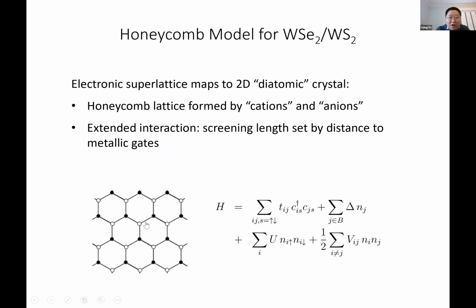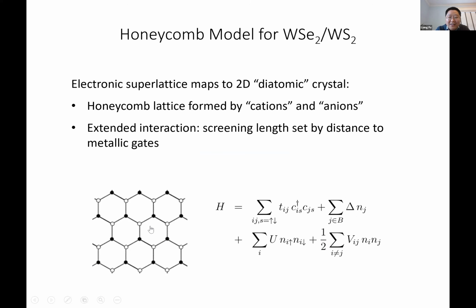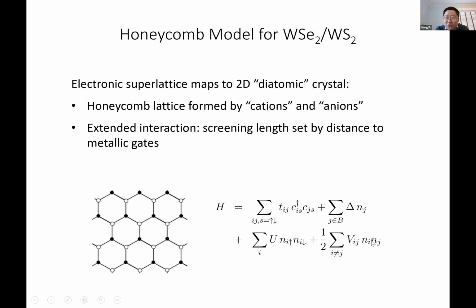It's a honeycomb model formed by two types of atoms. One can think of it as cations and anions. And we have hoppings between these sites. The two atoms have different on-site potentials, which we call delta. There's an interaction, both the on-site interaction, which we call U, and an extended interaction between first neighbor, second neighbor, etc. Here, with a Coulomb interaction, it's long range, it's 1 over R.